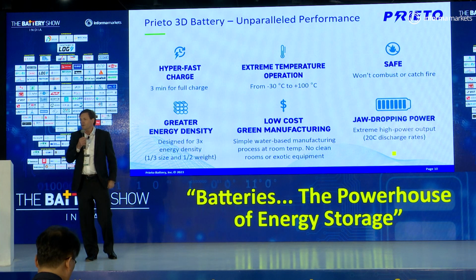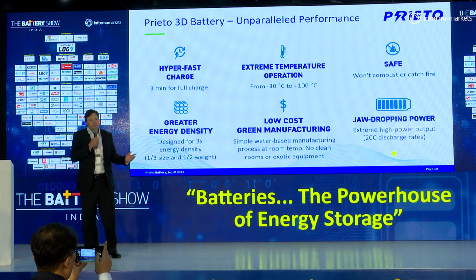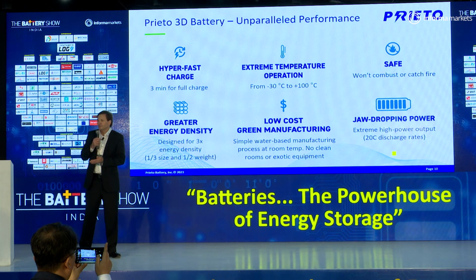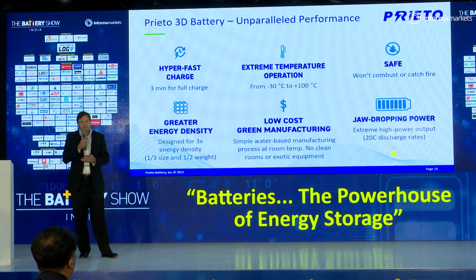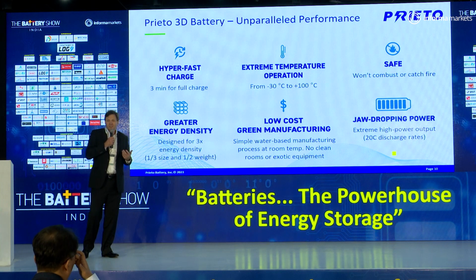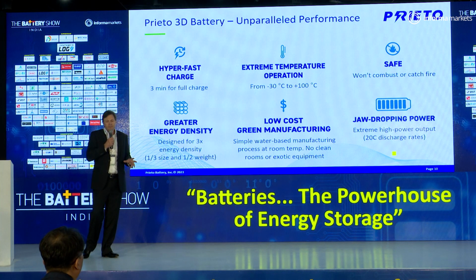Extreme temperature operation. Our battery operates from -30 all the way up to 100 degrees C. It not only operates, but it charges in both those extremes. Again, when you start looking at the Indian environment, to have a battery that can work up to 100 degrees C without any issues changes the way you design that battery, changes the way you design that pack, changes everything.